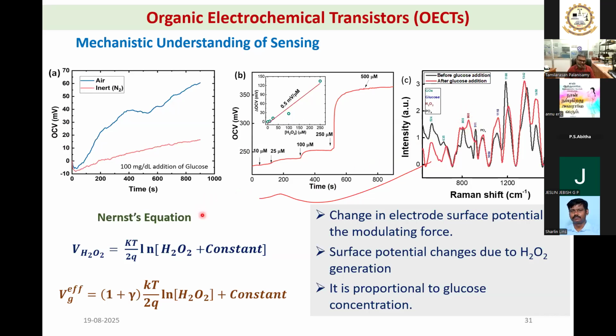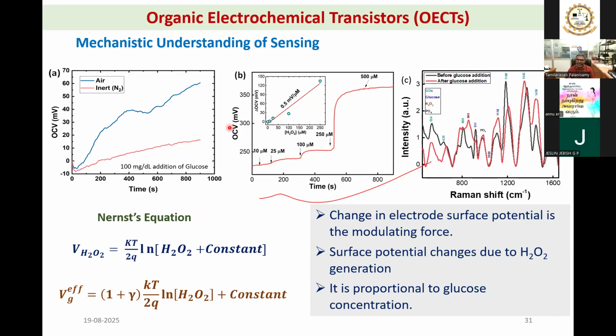So all these data tell us the mechanism: glucose is oxidized, and when it is oxidizing, your FAD is reduced, and the FAD is regenerated back by producing H2O2, and that H2O2 is generating the sensing signal. And this is as per the Nernst equation. When you increase the H2O2 concentration, your electrode potential, equilibrium potential, will change as per this equation.